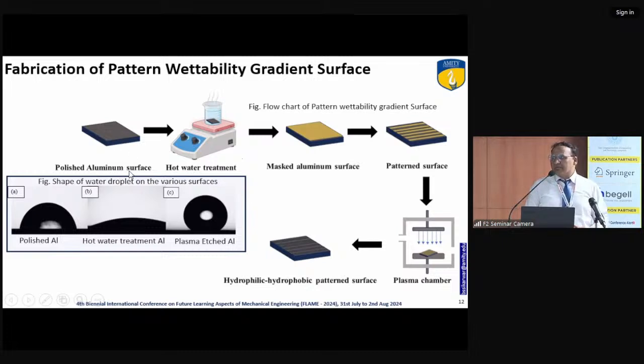First we polish the aluminum surface, then hot water treatment. Hot water treatment is nothing but putting the surface in water at a temperature of 100 degrees centigrade for 2 hours. What happens is a porous oxide forms. When dry, we mask the surface. Masking is nothing but putting tape. Then we mechanically and manually cut the strips, small and large. Then we do the plasma etching. After plasma etching, we remove the tape.